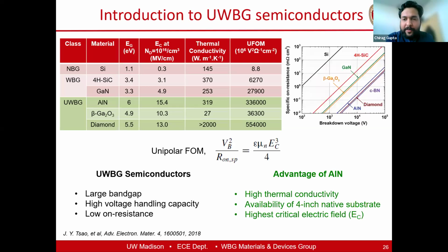Our choice is aluminum nitride, partly because there is a substrate available that has high thermal conductivity for power electronics. Thermal conductivity is extremely important. These days now we can get, or we are very close to getting 4-inch native substrates, which is great. Aluminum nitride offers very high critical field, and even if we take alloys of aluminum nitride, like high composition aluminum gallium nitride, we can get the advantage of high critical field. We can get heterojunctions in these devices. So all in all, at least in my opinion, it makes for a very good power electronics device.